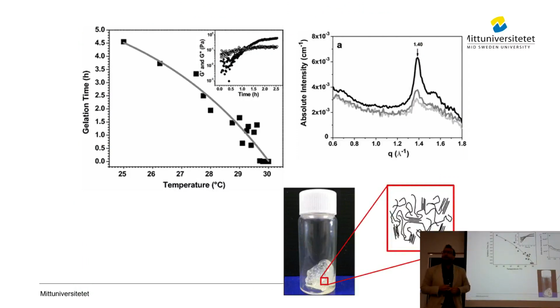And for instance, in the sodium hydroxide-based solvent, we observe that at room temperature, a solution can be maintained for a couple of hours very easily. As soon as we start increasing the temperature, the gelation time drops a lot and the solution is more prone to gelling. And we observed that during this gelation process, Bragg reflections were showing up. So that gave us an idea that some kind of crystallites were being developed there, working as a kind of bridge points between the cellulose molecules and eventually building up a 3D network that justifies this gelled state. Okay, so to make a long story short, to understand a bit of the mechanism behind the gelation.